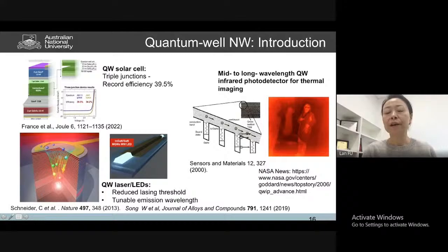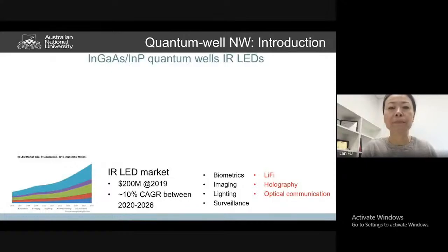And also, if we look at the transition absorption within the conduction band, we call it inter-subband transition, because these inter-subband energy levels have quite low energy. Thereby, you can use that for mid to long wavelength quantum well infrared photodetector applications. So you can really measure low energy photons for thermal imaging applications. So that is a very well-known application for quantum wells.